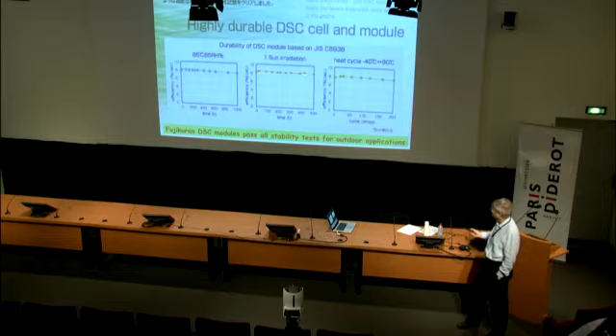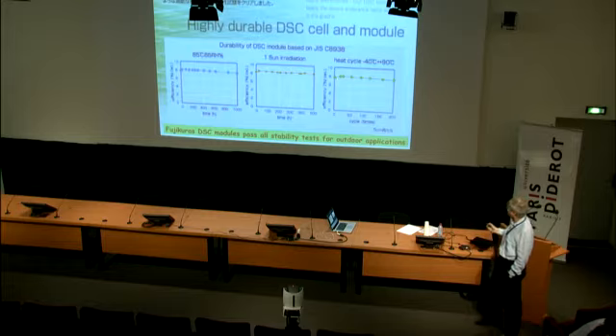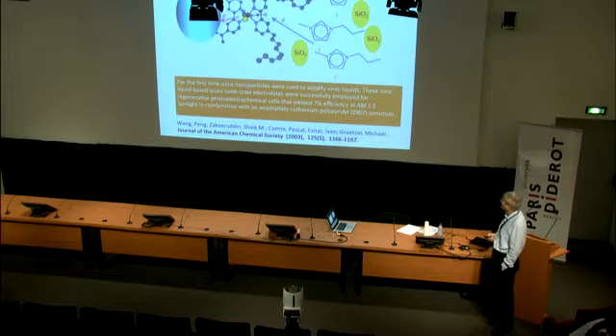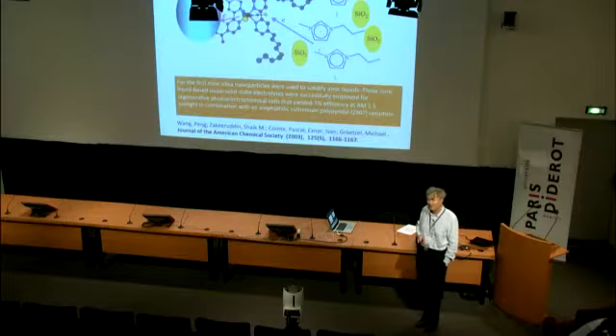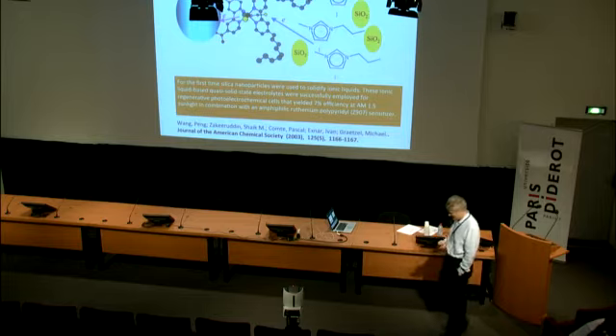You don't have a problem with photodegradation. Heat cycling is more difficult. You have to go back and forth between minus 40 and 90 degrees, 200 times. These tests are set by the international community, and if you pass them, you can show your client, I have a cell that is stable and can be used outside. And so it's not surprising that these cells use these ionic liquids solidified with SiO2 particles. These are the ionic liquids that Fujikura is using, but they're actually ionic solids. Once they are printed on, they turn solid, but they work as well or even better than the liquids. That's amazing. It's a gel, really, but it's amazing that this happens.